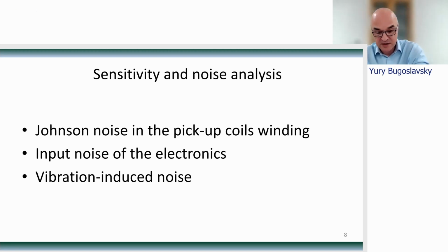If you think about the signal-to-noise ratio, the minimum detectable signal is determined by the amount of noise present in the detection circuit. The sensitive element here is a set of coils wound in thin copper wire. The coils have finite resistance, and therefore at a given temperature, they will generate Johnson noise due to thermal effect.